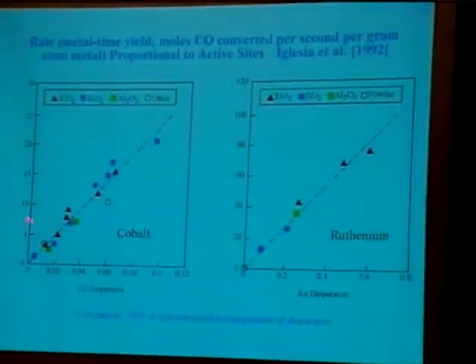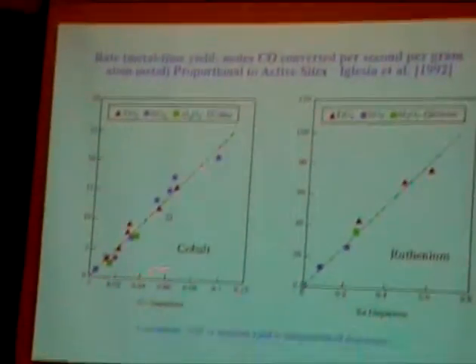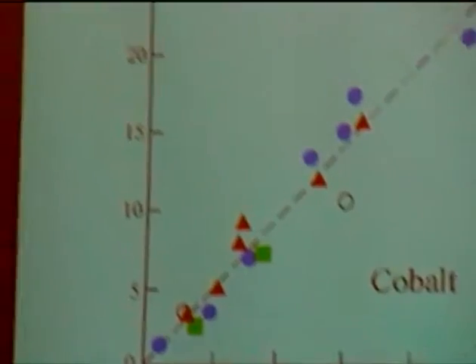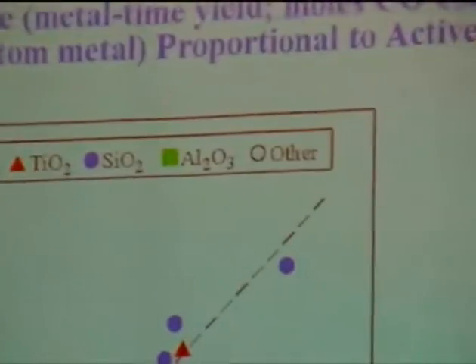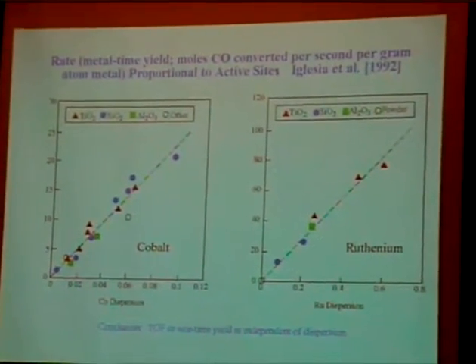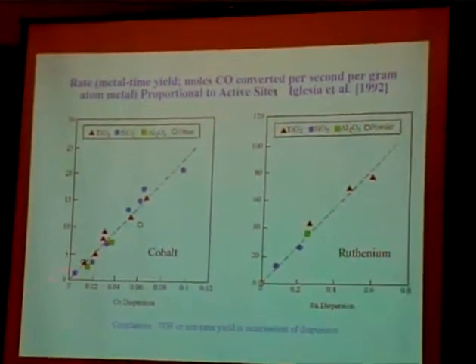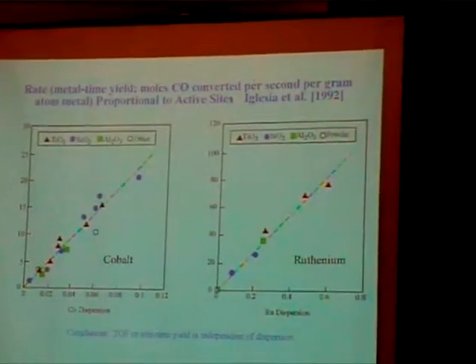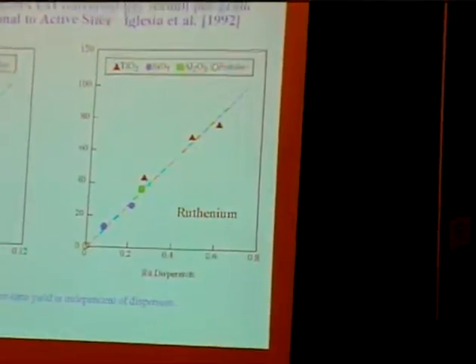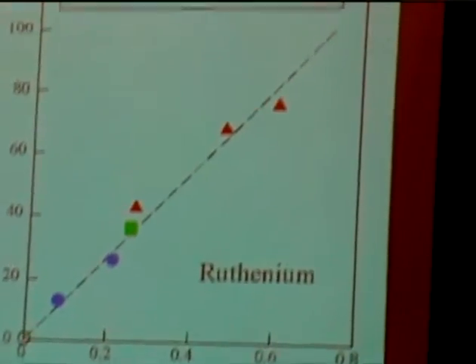Here are some of their activity data — mass-based rate activities as a function of cobalt dispersion for a suite of catalysts prepared on different supports, albeit at relatively high loadings. So the support effects are minimized, and we see a very good correlation of activity with hydrogen uptake. That's important because it means you can use hydrogen uptake as an indicator of activity.